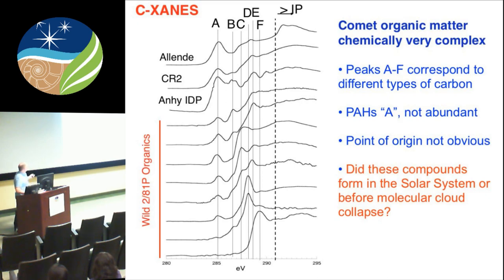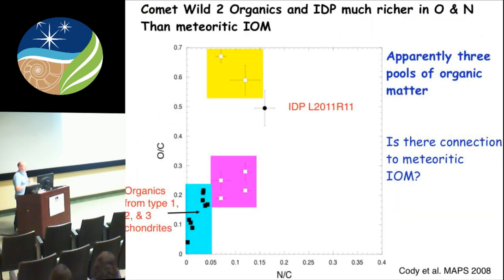Now, one of the things we can also do is measure oxygen to carbon ratio and nitrogen to carbon ratio, which is a very handy thing to do when your particles are at submicron scale. When we did that, this is Cody and Marilyn Fogel's work, and it's just a couple of dots here, but they've filled this in with probably hundreds of meteorites by now. This is the full range of what you would find for chondritic organic matter, IOM. So up to, say, 5 nitrogens per 100 carbons, and maybe up to 24 oxygens per 100 carbons. And what we found was comet particles were richer in nitrogen and oxygen, and there seemed to be two groups that were distinct both in their molecular spectroscopy and in their elemental chemistry.